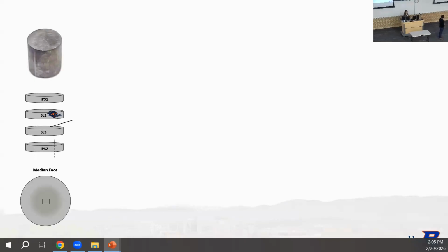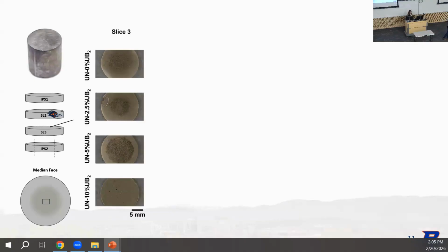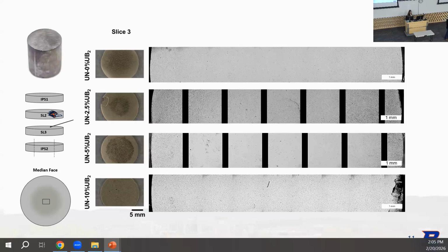We looked at the different faces under SEM, and as we started prepping these samples, we started noticing this coring effect. Under SEM, we discovered that this was really due to a difference in the porosity, which is interesting because we were not expecting this, but this was also seen in other studies. So something that we're doing is looking a little bit closer at this and trying to understand if there are any differences in phases, or if this affects the properties even.